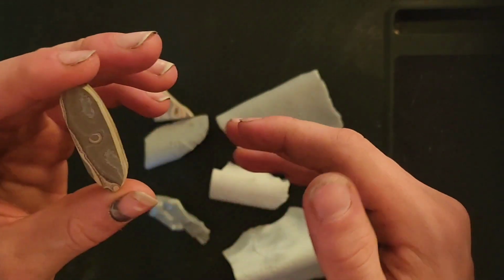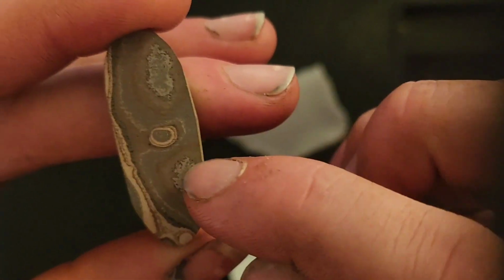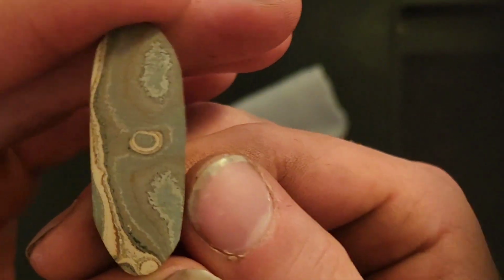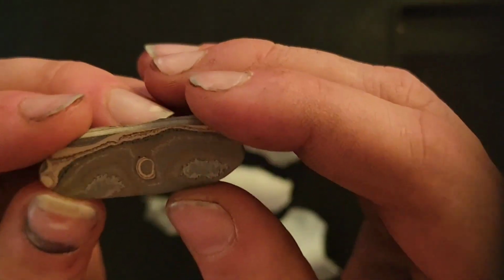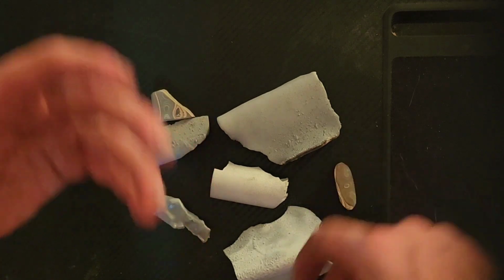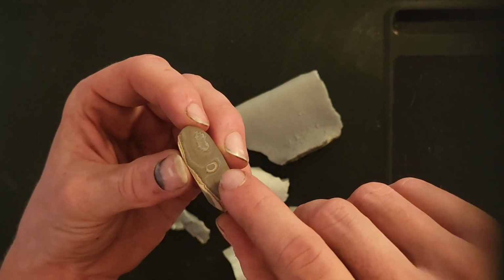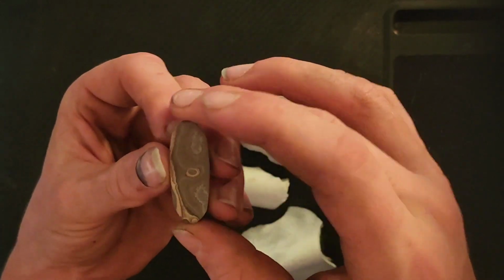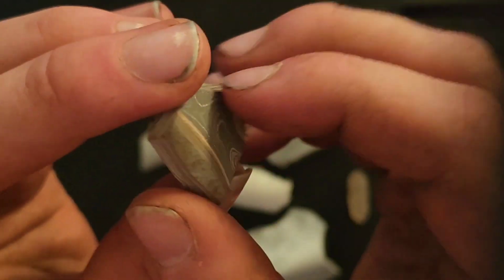The first one has to do with its properties. Because it's made of multiple layers of spray, any slight imperfections get multiplied time and time again. As you can see, there's a ring right there in this particular piece. That's probably caused by a small piece of sand from the sandblasting that a piece of material has to go through before it gets painted, somewhere back here or in the middle of this stack. That small piece of sand gets covered in paint, baked, covered in paint, baked, over and over again, and each of those layers slightly increases the size of that bump. Eventually you end up with little circular patterns like that, or even little curls like that one there has.